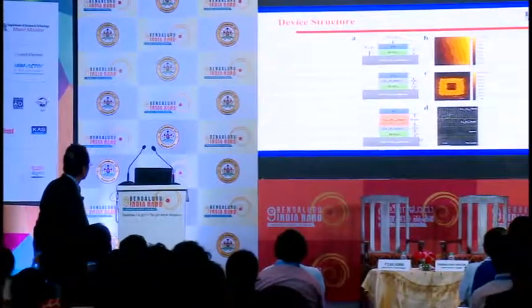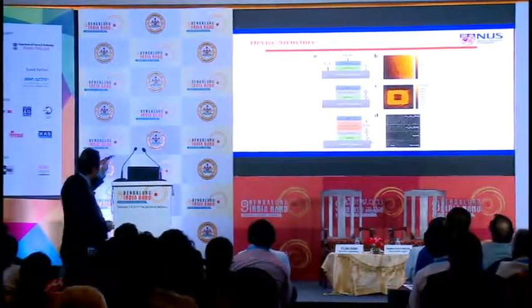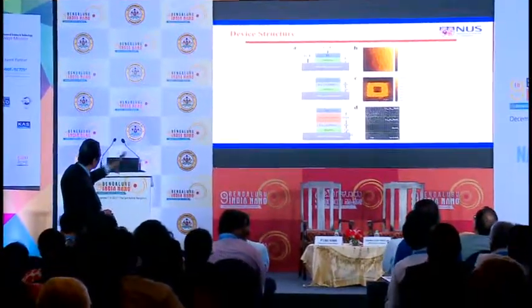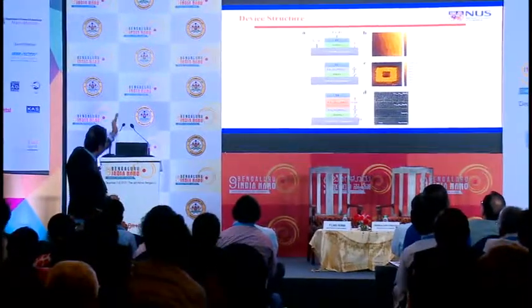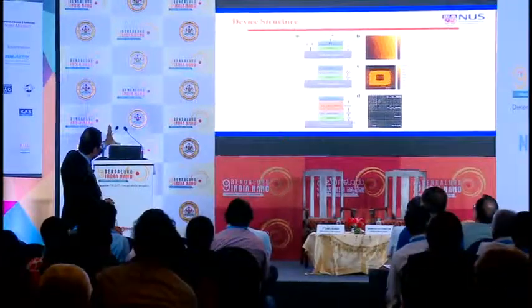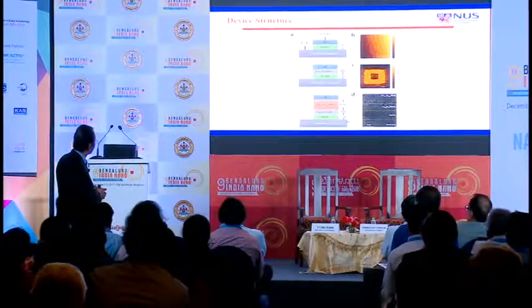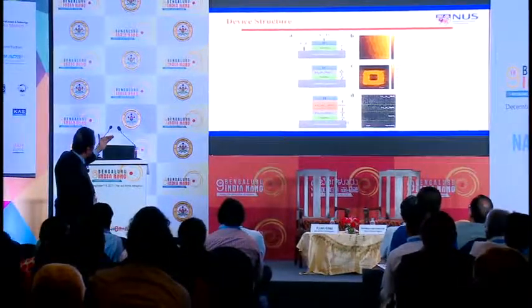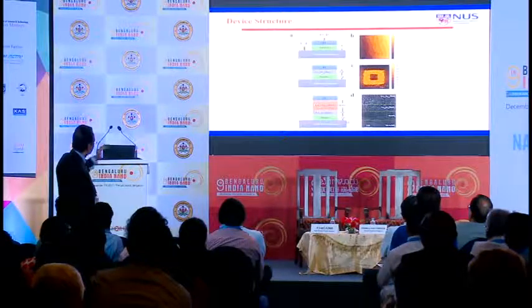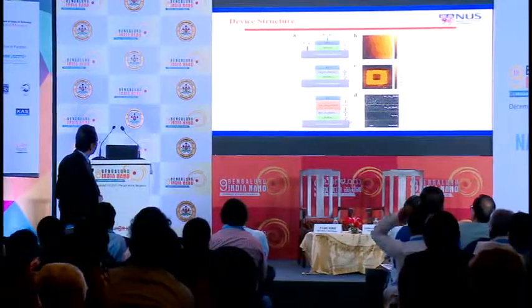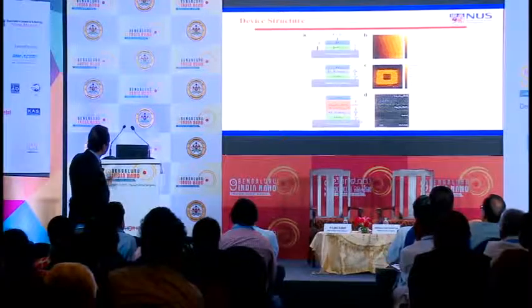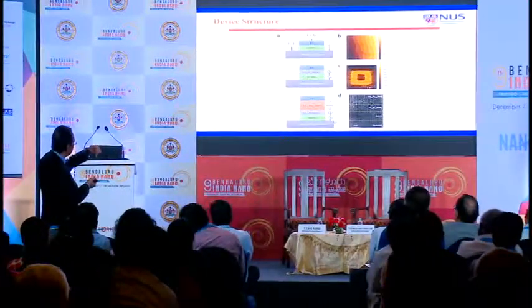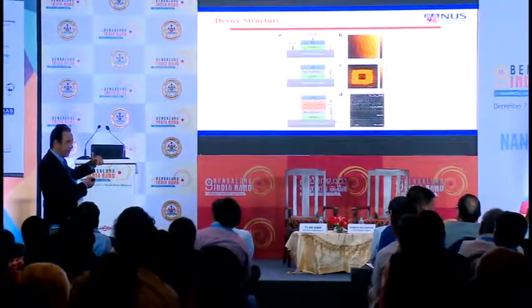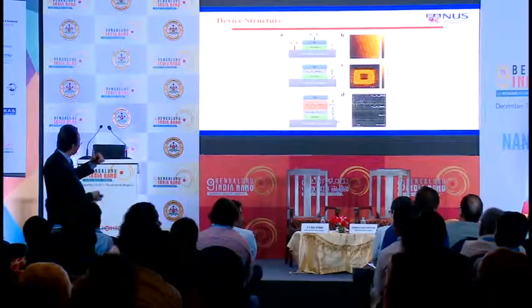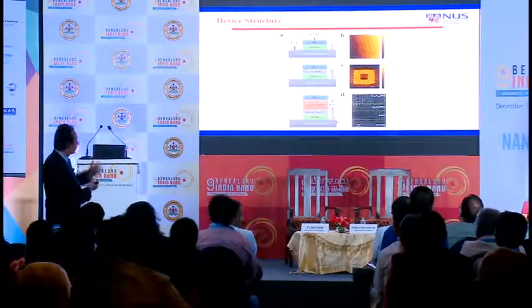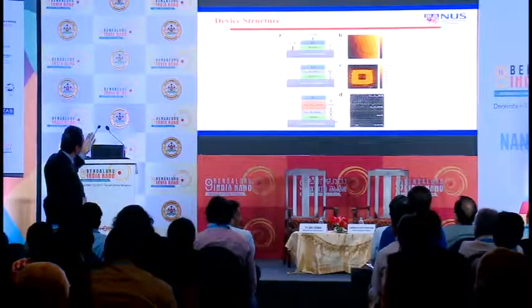So we make three different types of device structures. The substrate is niobium-doped strontium titanate, because all the structures are crystallographically known. They're all epitaxial, even though they're thin films. And the bottom substrate is niobium-doped strontium titanate, which is conducting. You grow a ferroelectric layer, barium titanate, and then you put platinum on top. So it's like a capacitor, and you measure the resistance across it, and the electrons travel through tunneling. It's what's called tunneling resistance.